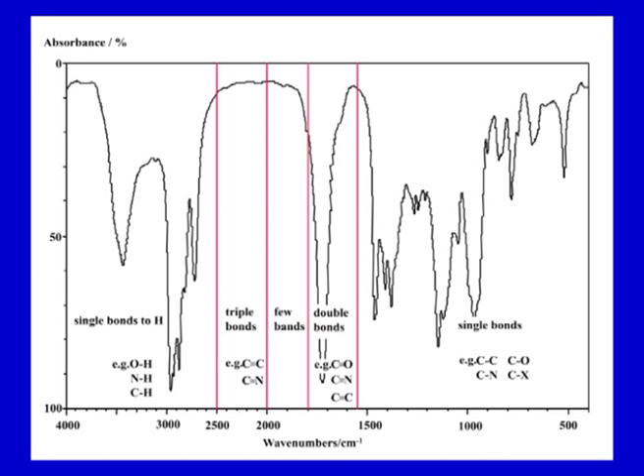So, the strong absorption bands or characteristic spectra in a particular region of wave numbers, say from 4000 to 2500 per centimeter, usually come from stretching vibrations between hydrogen and some other atom of low mass. The OH and NH stretching frequencies fall in 3700 to 2500 per centimeter, with various intensities. Hydrogen bonding has a significant influence on the peak shape and intensity, so that is also very important. Then the CH stretching bands occur in the region of 3300 to 2800 per centimeter, and we can go on, where different kinds of compounds, aliphatic, saturated or double bond compounds, have characteristic spectra. Different regions could be taken.